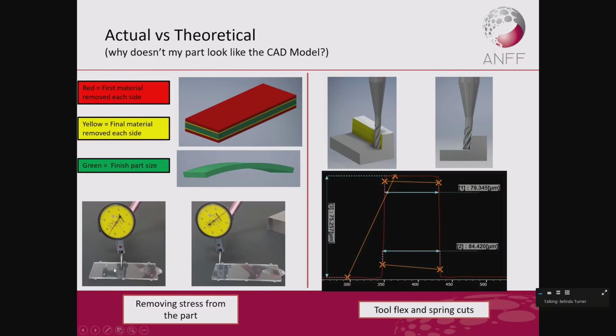We've got an injection moulded part here, and you can see at the end it's gone 0.35 millimetres from the middle to the end where it's bowed, because obviously this has been generated by melting polymer, putting it into a mould and coming out. If we haven't quite got those parameters right, then there's a lot of stress in that, and as soon as it comes out of the mould, it starts to distort.